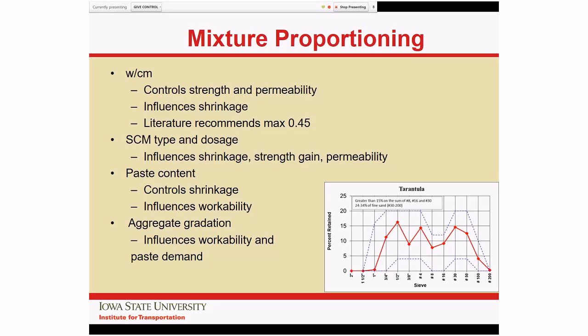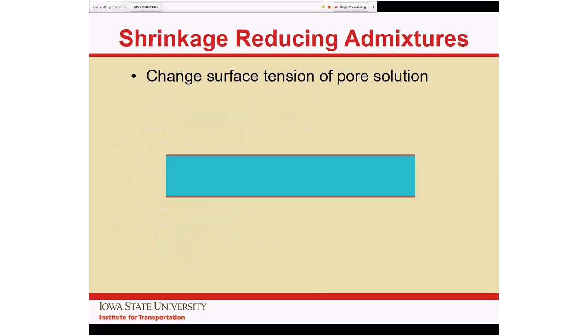And so we come to the aggregate gradation, is that if we have a system that is well graded, then we can get better workability and yet at the same time control the amount of paste that we need. For pavements, we are recommending staying inside what is called the tarantula curve, and that envelope is shown on the bottom right-hand side of the slide. There you're getting the sweet spot between good workability and at the same time as much aggregate in the system as we can possibly get. And both of those are good things.